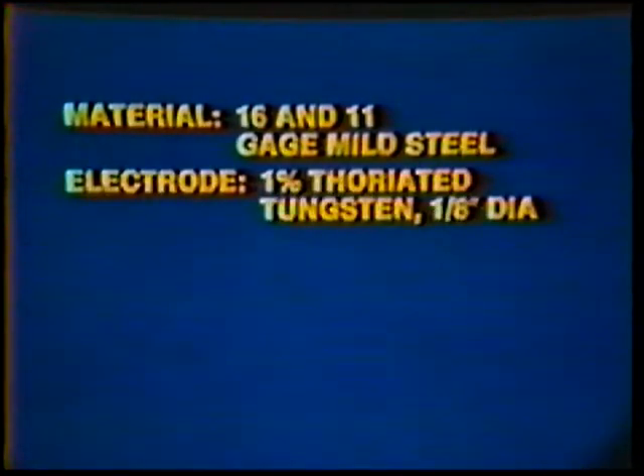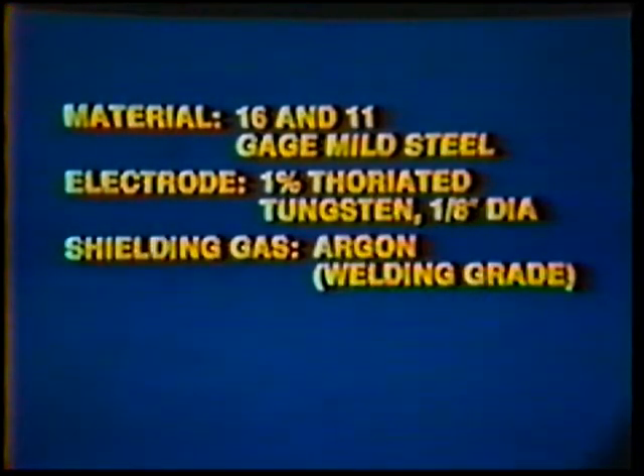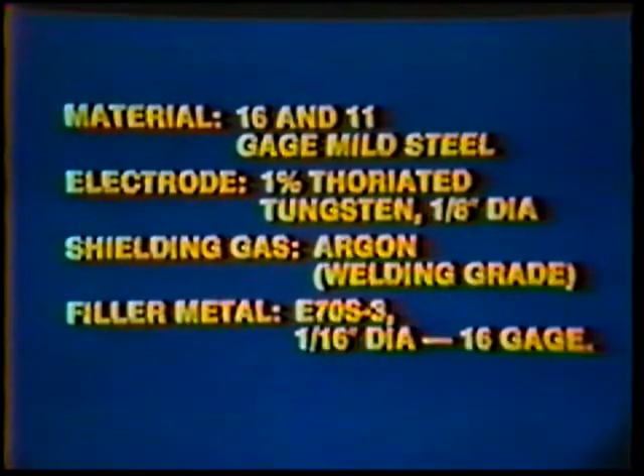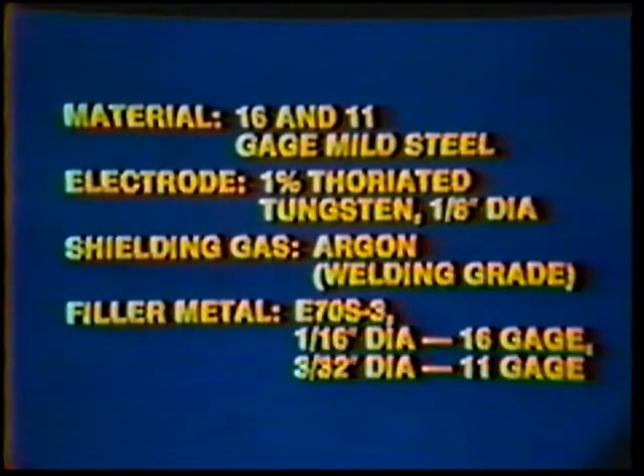Material: 16 and 11 gauge mild steel. Electrode: 1% thoriated tungsten, 1/8 inch diameter. Shielding gas: argon, welding grade. Filler metal: E70S3, 1/16 inch diameter for the 16 gauge and 3/32 inch diameter for the 11 gauge.